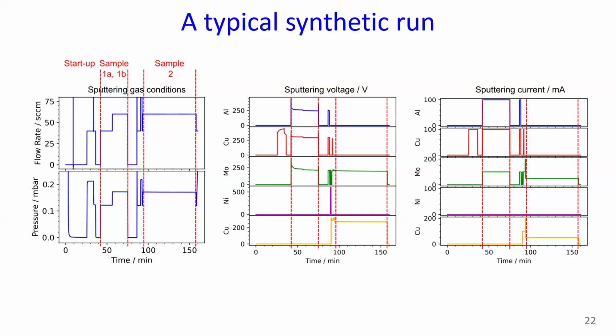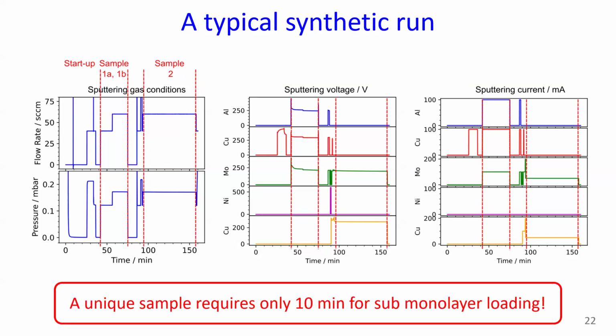And also, most importantly, we're sputtering a beam of particles: change the current on one of the targets, and that's a new catalyst system. And it takes 10 minutes to deposit one sample, depending on how much loading you'd like, but compared to conventional routes, where it might take 1 day to synthesize a new material.